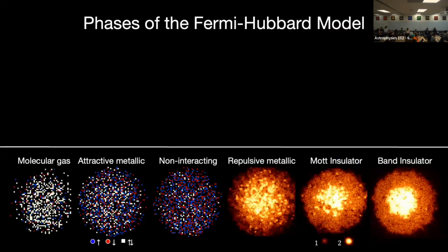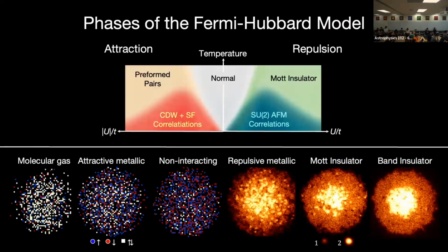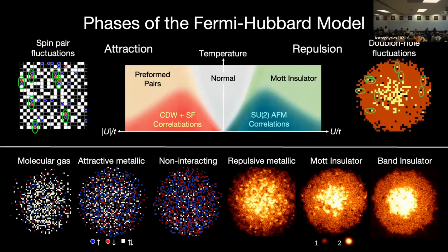Okay, cool. That summarizes what we can study in these Hubbard systems. We can study the repulsive side, the attractive side. There's a beautiful mapping that I hid from you between the repulsive and the attractive side. So these doublon-hole fluctuations on the repulsive side are nothing else than the up-down fluctuations of my pair on the attractive side. There's a one-to-one mapping by mapping the spin-up particles to spin-ups and the spin-down particles to holes. Kind of cute, two sides of the same metal. That works for any lattice that is so-called bipartite, like can be split into two equivalent sublattices. So our square lattice does that.